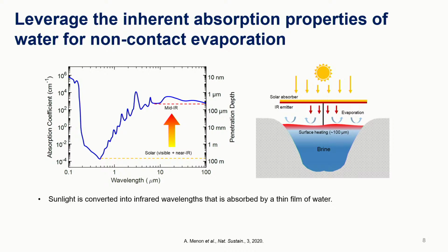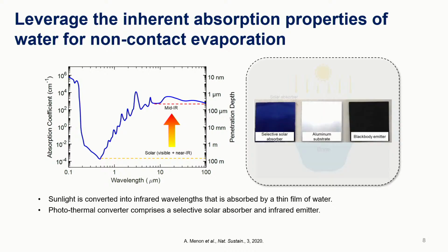So there's no contact between this top layer and the solution we're trying to heat. So we don't need a porous absorber, a wick, or any insulation material. You just have to have a selective solar absorber and an infrared emitter, and then you're using thermal radiation to transfer that energy to the water surface, and it'll absorb strongly within a few microns. And so you get this surface heating effect, but with a completely non-contact type of system.